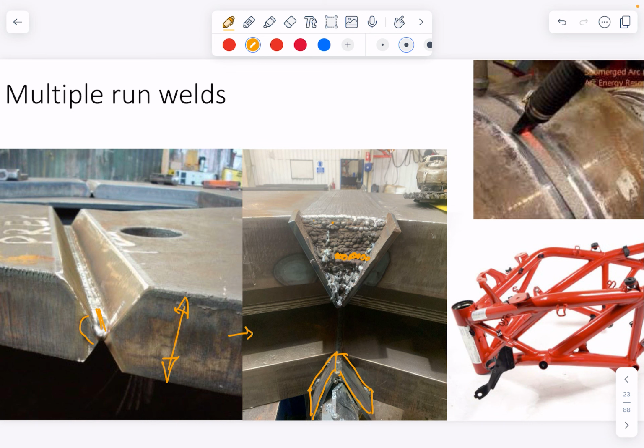These beads of weld would have been done with what's called a submerged arc, which I didn't mention. But if you imagine a really, really big MIG welder with a continuous wire feed, but the wire is perhaps 3 to 4 millimeters in diameter. But unlike a MIG where you're using a gas as a shield, you use a granular flux. So it only works in a downhand position. You pour the flux on the job, you automatically index it, it's on a little robot that runs along the weld, feeding the wire in at the right rate. You can see the completed weld underneath the slag.